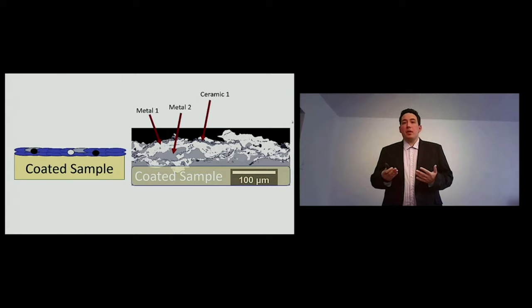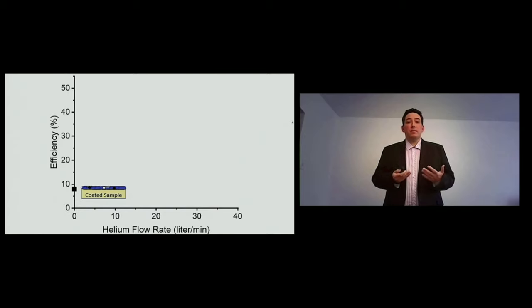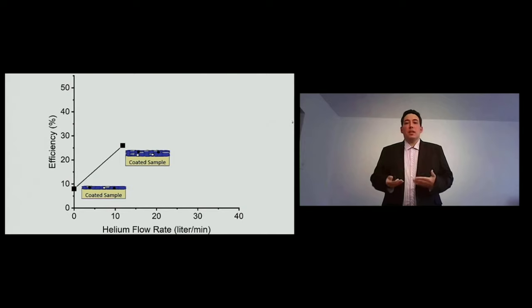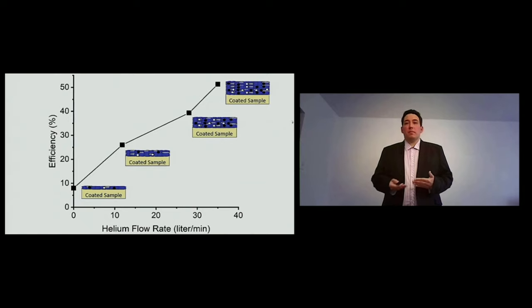In order to test that theory, what we did is a set of experiments, and we increased the flow rate of helium on the spray. Well, the helium has an effect of helping the heat transfer between the particle and the stream and makes the particle heat more. Furthermore, it also increases the temperature of the stream. As we start increasing the amount of helium, we start noticing more and more coating being deposited, up to the moment that we reached the limit that we had in the equipment, and we also didn't want to burn the samples any more. So if you heat too much, the sample might be burned.